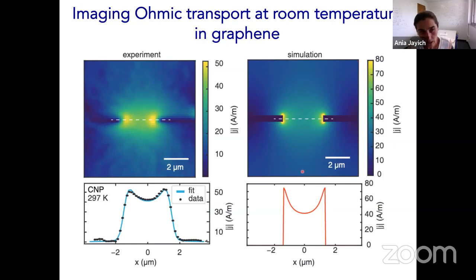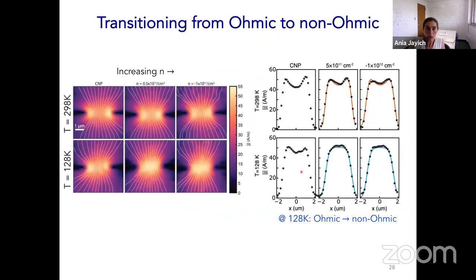But to say that the experiment and the simulation fit each other very well. So starting at room temperature in the ohmic regime, we have done experiments where we varied the temperature. Interestingly, here I show you the room temperature data. We're at room temperature at charge neutrality, relatively low density of electrons. Again, we see ohmic behavior.